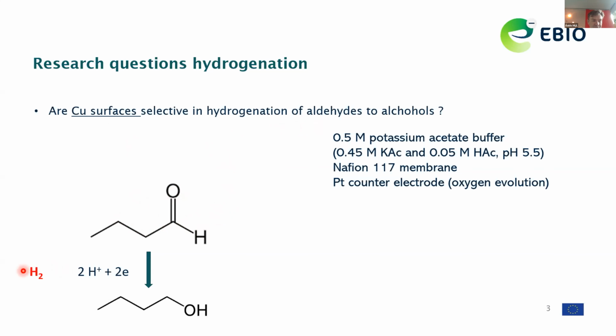With respect to the evolution of hydrogen, of course, in the hydrogenation reaction, you would like the aldehyde to be converted to the alcohol and not generate any hydrogen, which suppresses the Faraday efficiency of the aldehyde to make the alcohol. We used a buffer solution of potassium acetate, 0.5 molar. We used a Nafion 117 membrane, a classical H-cell setup that Sigi has shown to you already. And in the counter compartment, we had a platinum gauze to produce oxygen in the electrolysis.